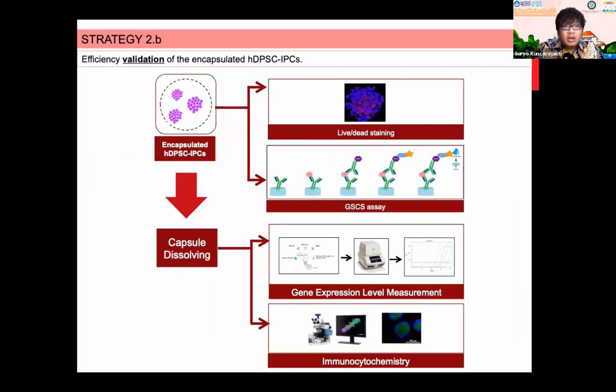After IPC encapsulation was performed, the functional and viability assays of the encapsulated IPC were performed in this study as well. The first evaluation included the viability of the encapsulated IPC by using live death staining, and also we did a glucose stimulated C-peptide secretion assay to check the C-peptide level produced by the encapsulated IPC by the ELISA. And also we tried to dissolve the capsule by a chelating agent in the citrate buffer, like EDTA, and the capsule will be dissolved, and then we recollect the IPC and check again the gene expressions related with the pancreatic marker, and also we confirm with immunocytochemistry study as well.